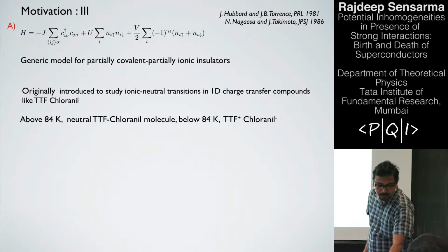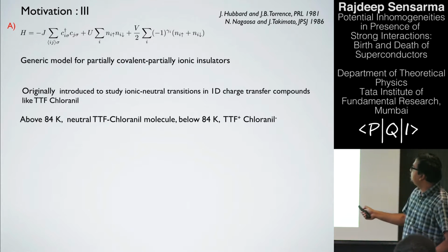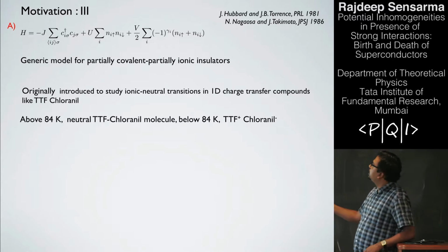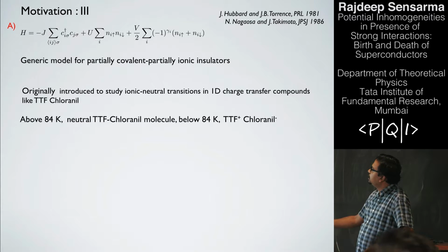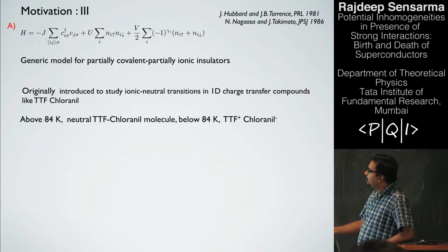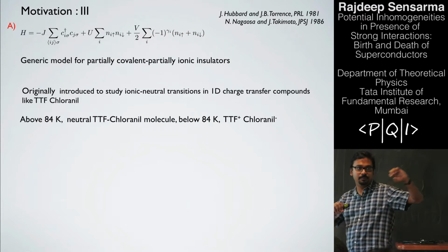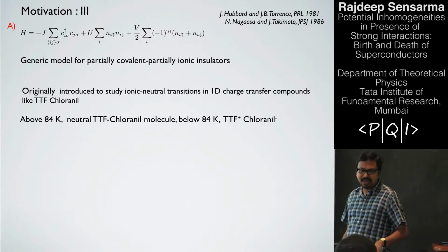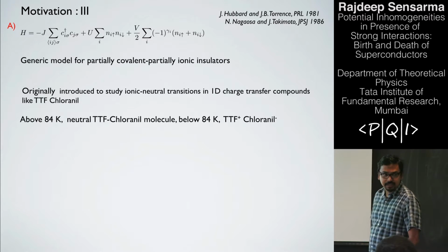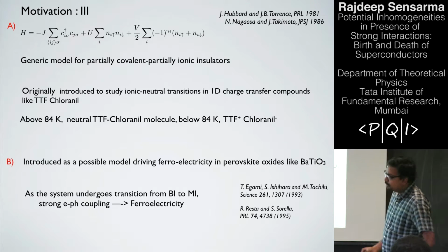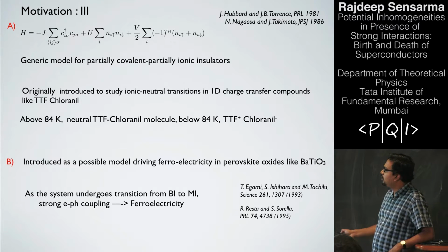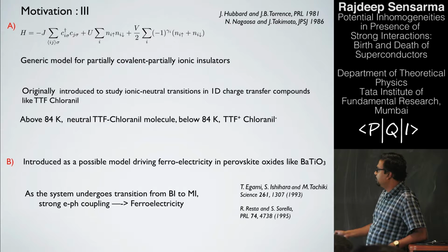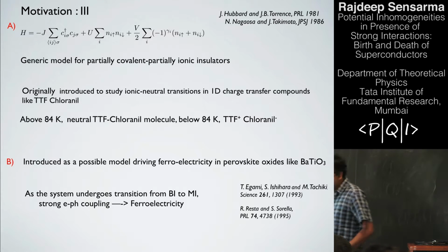Motivation 3 is that this is a model which, at least for 1D, was introduced in '81 by Hubbard and Torrance to study 1D charge transfer compounds like TTF chloranil. Basically above 84 Kelvin there is a neutral molecule, and below 84 Kelvin it just breaks up into TTF plus and chloranil minus, and this model was used to study that transition. It was also introduced as a possible model driving ferroelectricity in perovskite oxides like barium titanate.